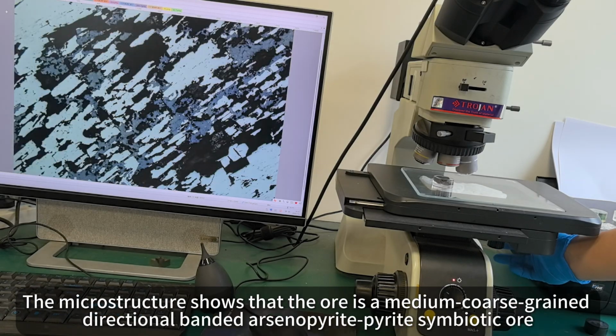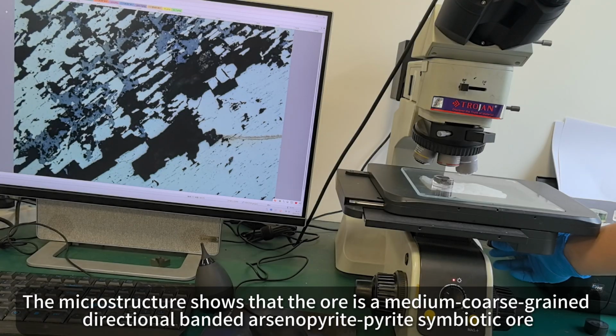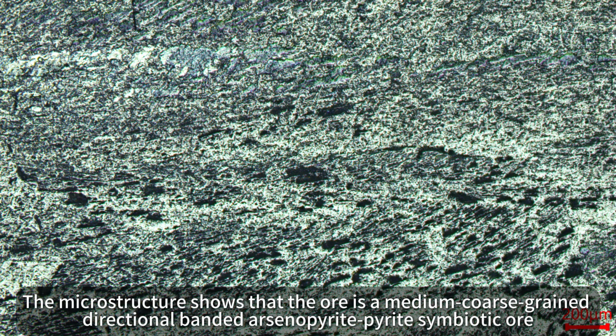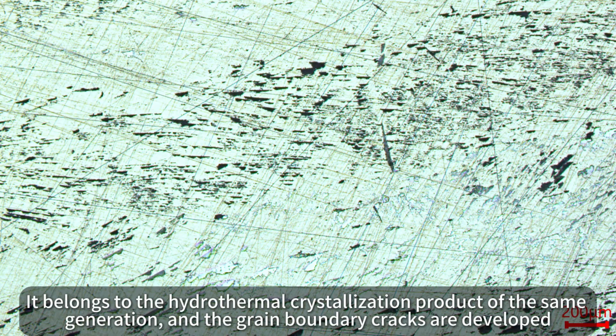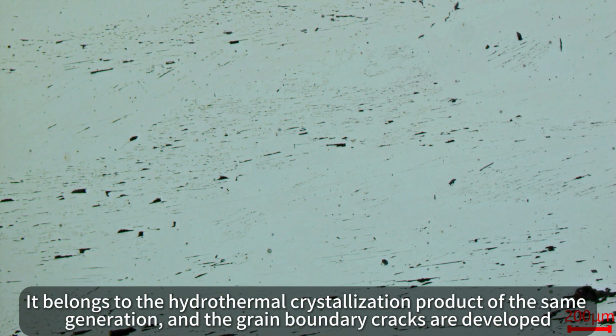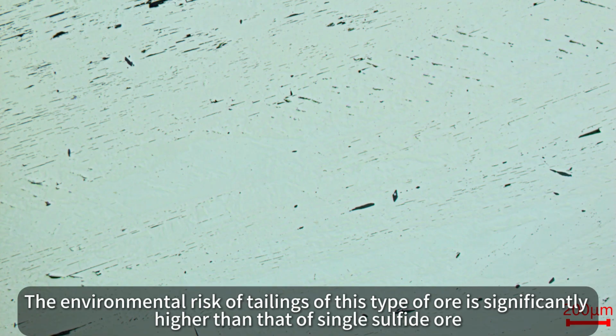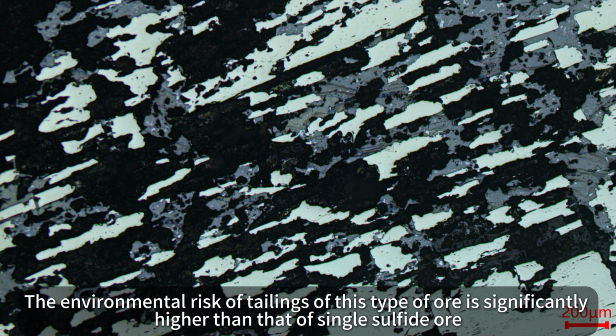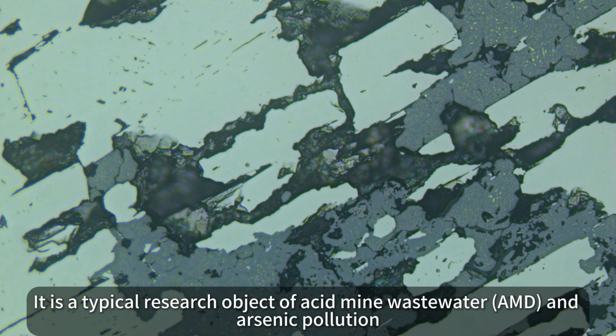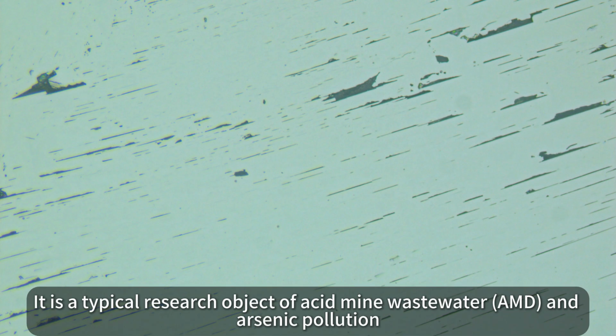The microstructure shows that the ore is a medium coarse-grained directional banded arsenopyrite-pyrite symbiotic ore, belonging to the hydrothermal crystallization product of the same generation, and the grain boundary cracks are developed. The environmental risk of tailings of this type of ore is significantly higher than that of single sulfide ore. It is a typical research object of acid mine drainage, AMD, and arsenic pollution.